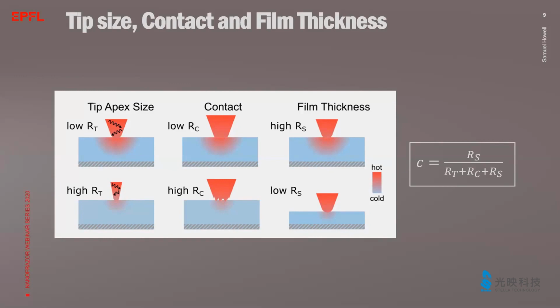The film thickness is important for the thermal isolation in order to reach reasonable temperatures of a few hundred degrees, as discussed before. As the thickness of the film decreases, the influence of the thermal conductivity of the substrate becomes more important. Typically, a couple of tens of nanometers of a polymer film on a silicon wafer are already enough to reach sufficiently high temperatures at the interface.